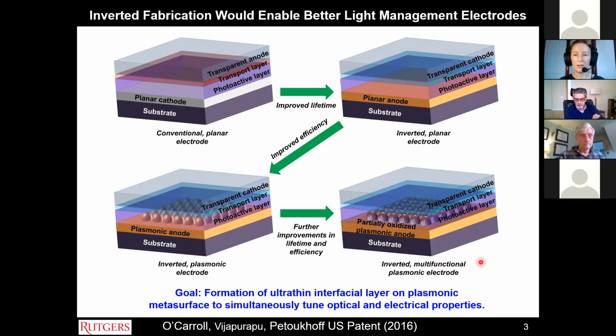So if our goal then is this inverted structure where the metal serves as the anode for hole injection or collection, as that's how we define it in the organic optoelectronic community, and then with metal structures on it, then ideally to improve efficiency and lifetime. Our initial idea was to help with charge injection or collection by partially oxidizing the metal, in this case the silver, because you'll form p-type semiconductor hole injection layers or hole collection layers.